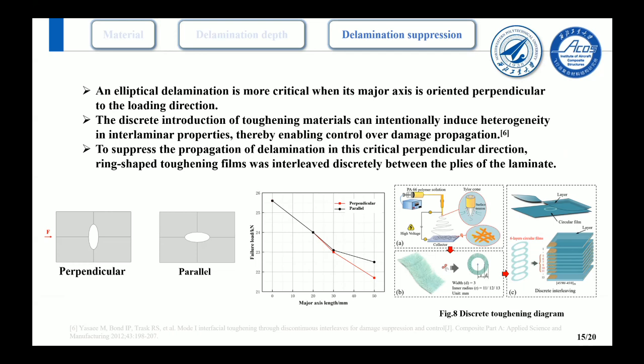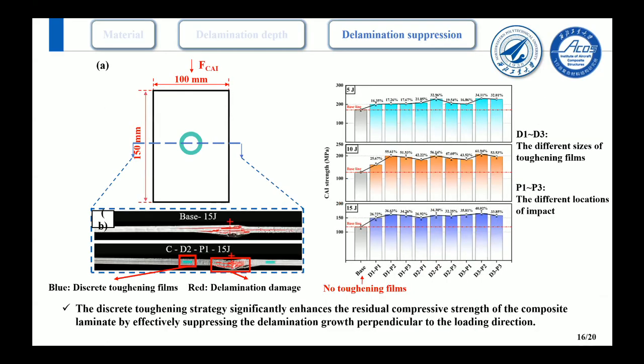Introducing toughening materials at the interfaces of composite laminates can enhance their interlaminar fracture toughness. To suppress the propagation of delamination in this critical perpendicular direction, ring-shaped toughening films were interleaved discretely between the plies of the laminate. As shown in the figure, the results from the low velocity impact and subsequent compression after impact tests are presented. It can be concluded that the discrete toughening strategy significantly enhances the residual compressive strength of the composite laminate by effectively suppressing the delamination growth perpendicular to the loading direction.